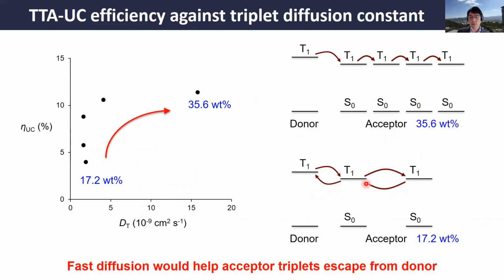We are thinking this way. At the lower concentration of 17%, the triplet diffusion is not very fast, so that after energy transfer, the triplet cannot move away quickly. So it's going back, and then eventually some goes back to the donor. But with the high triplet diffusion at higher acceptor concentration, the triplet can diffuse faster, so it can escape from the donor and then undergo TTA before going back to the donor.